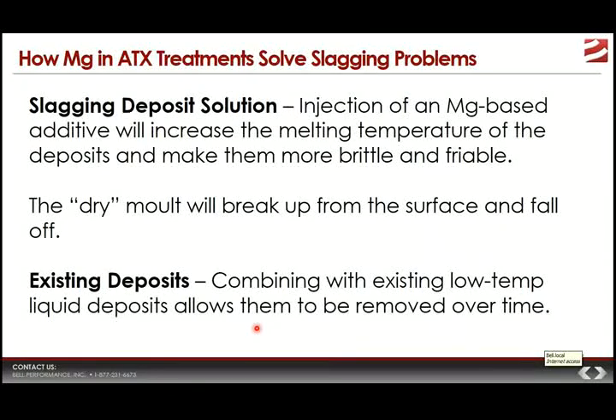Now, we have mentioned magnesium multiple times. It's time to look a little bit more closely at how magnesium in ATX solves slagging problems. First thing, we've already shown that it's been demonstrated in the field that magnesium helps to fix slagging problems. If you inject or add a magnesium-based additive into the HFO, when that fuel oil is burned, that magnesium will actually act upon the deposits and will combine with them. And the resulting combination deposit actually has a much higher melting point than it did before. With the higher melting point comes a significant change in its physical characteristics. They're more brittle. Sometimes in the industry, they will use the term friable. All that means basically is that they're almost dry, and they will actually break off from the surface and fall off over time.